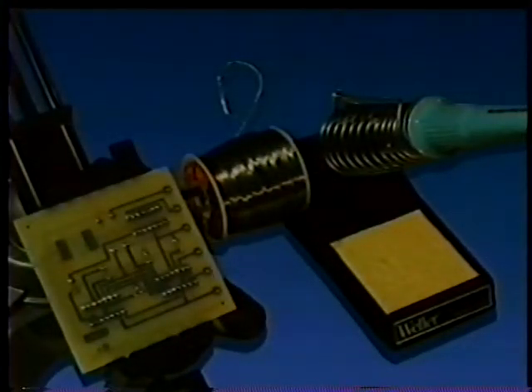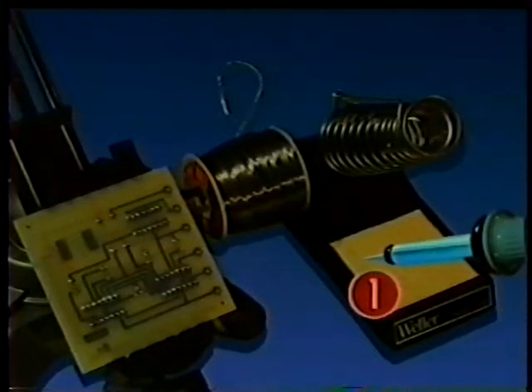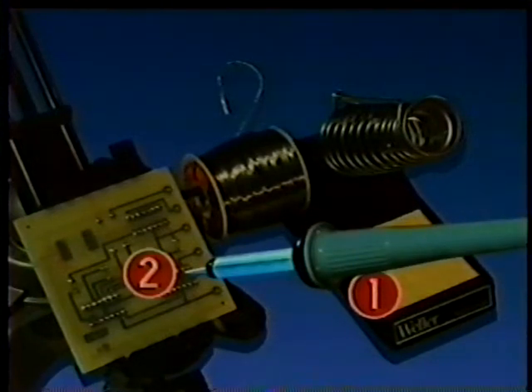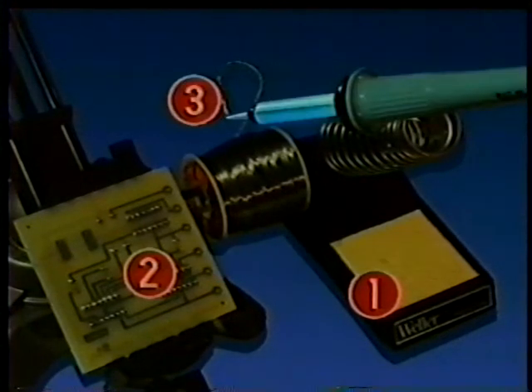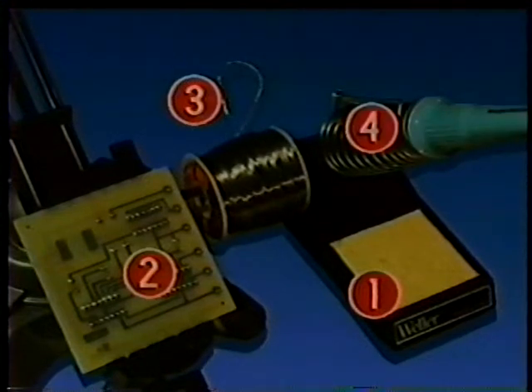The first step in the actual soldering cycle is to wipe the tip on a clean, damp sponge. This is necessary because as the iron idles in the holder, the hot metal of the tip interacts with air and solder to create the troublesome oxides. Make the solder joint. Heat the work with the tip. Melt the solder on the side of the work away from the tip. Re-tin the tip. Just a touch of solder to protect the metal of the tip. Return the iron to the holder.